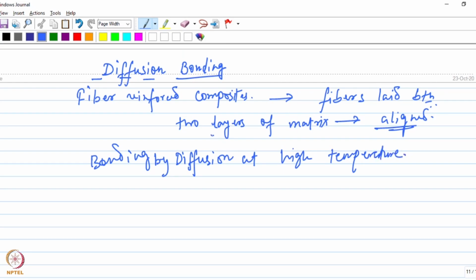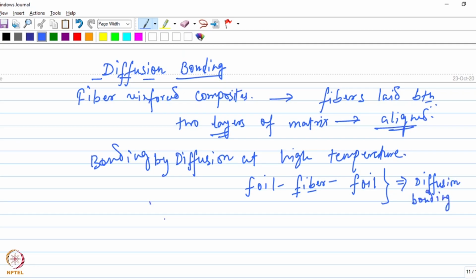But these layers are generally very thin. So this technique therefore is also referred to as foil fiber foil method. So in between two foils of metals, two thin layers of metals, you have the fibers, and this assembly is bonded by diffusion when you heat it to high temperature. 6061 aluminium boron fiber composites have been processed by this technique,